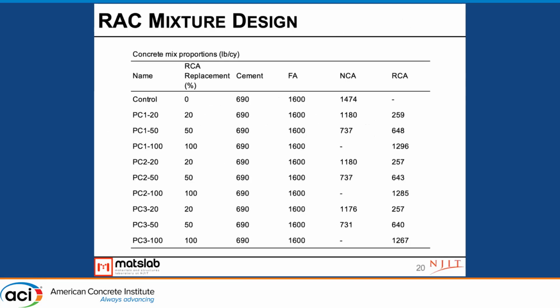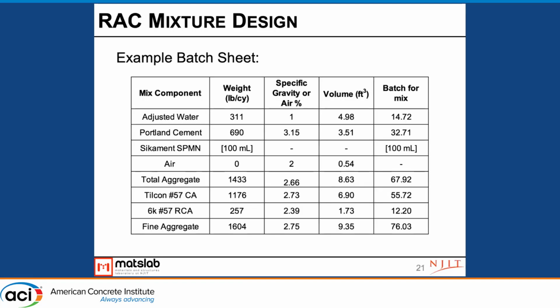So then this is just some of the proportions in the mixture. As you can see, we have very consistent weights of cement, fine aggregate, and even our admixtures. The only thing we're changing is the RCA by volume. So what you end up with is, as you increase your RCA percentage, your unit weight goes down, because RCA is less dense than a natural aggregate due to the attached mortar phase. We're trying to keep the volumes as consistent as possible. So as we increase our RCA content, the unit weight of that system is actually going to decrease.